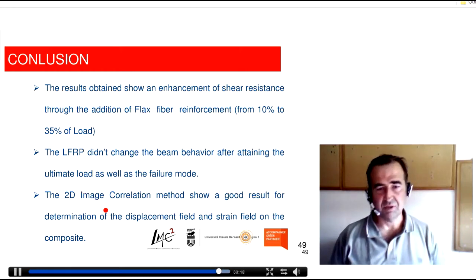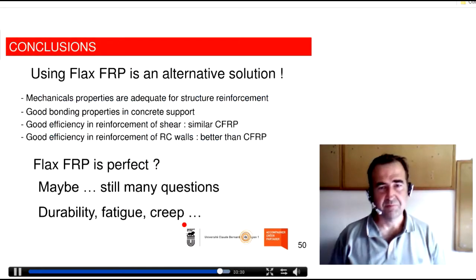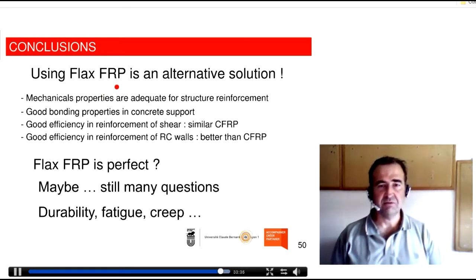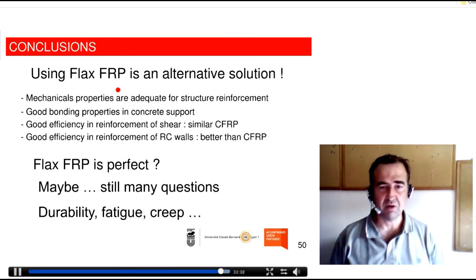The DIC method, as we've seen, is very interesting to investigate the strain localization and the strain values we can obtain on flax fibers. So flax fibers may be a very interesting alternative solution to use instead of carbon fibers in some specific areas where we don't really need an important Young modulus, unlike maybe in flexural strengthening or confinement, where Young modulus is more important. It's some investigation we have to continue in the lab.